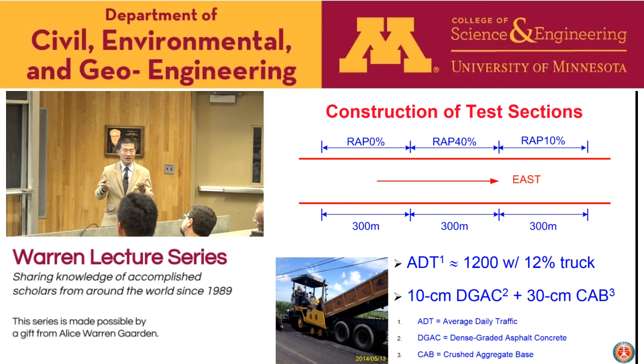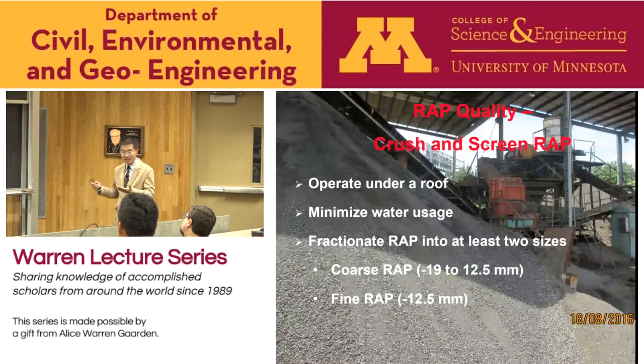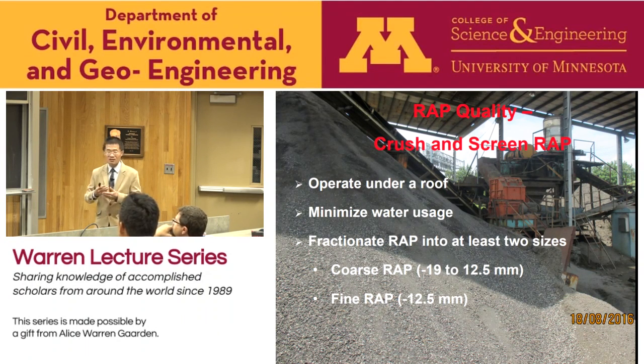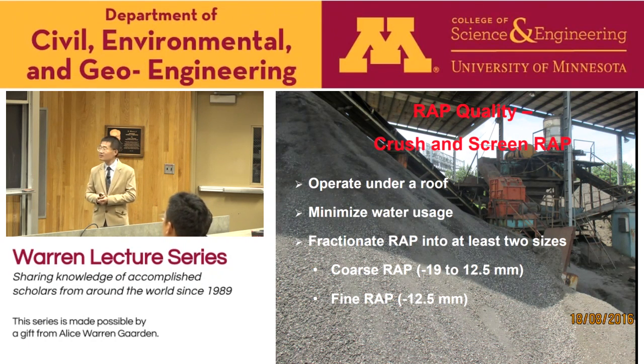Using this test road as an example, I would like to show you how we control the RAP quality and RAP mix quality. It's essential to crush and screen the RAP materials under a roof to keep the RAP material dry. And we take great care to minimize the water usage during the crushing operation. To maximize the RAP usage and still meet the gradation, volumetric properties, and mechanical properties, it's necessary to fractionate RAP into at least 2 sizes. In this study, the RAP material is split into the coarse RAP material, which stays on the 12.5 millimeter sieve, and the fine RAP material, which passes the 12.5 millimeter sieve.